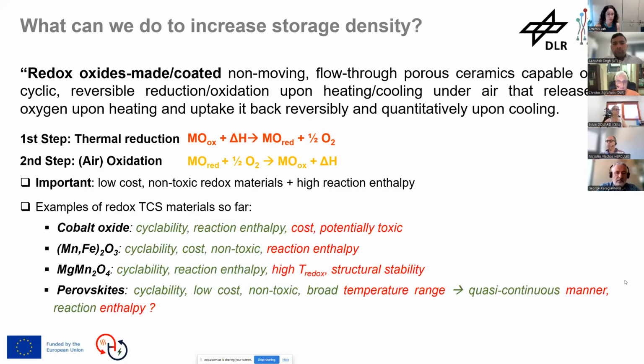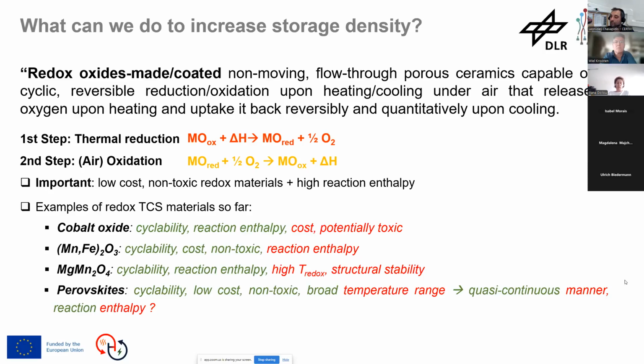The materials that have already been chosen and tested for this kind of applications span this range that you see there. With green are the desired properties that each material has, with red, the adverse ones. You can see, for instance, that cobalt oxide has extremely good cyclability and high reaction enthalpy, but it's of high cost and potentially toxic. Manganese iron mixed oxides are also non-toxic and cheaper, but they have lower reaction enthalpy. Other concepts, mixed magnesium manganese oxides, have high reaction enthalpy and cyclability, but they need a very high temperature to initiate the thermal-only reduction that is mentioned as the first step above. And perovskites, which we will elaborate upon, have cyclability, low cost, are non-toxic, and can operate in a broad temperature range, but the reaction enthalpy is not as high as the previous one.